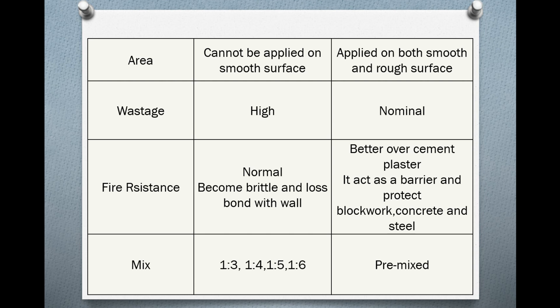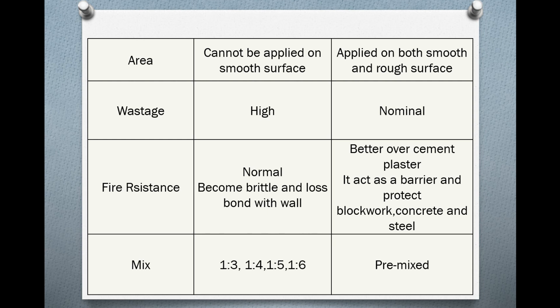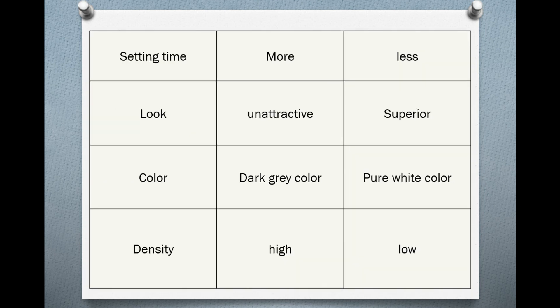Next: mixed proportions. For cement plaster, we use mix ratios of 1:3, 1:4, 1:5, or 1:6 (cement to sand). For gypsum plaster, we simply add water to gypsum powder. Regarding setting time, cement plaster takes more than 24 hours to set, and painting can begin after 72 hours. Gypsum plaster sets faster, allowing painting after approximately 34 hours.